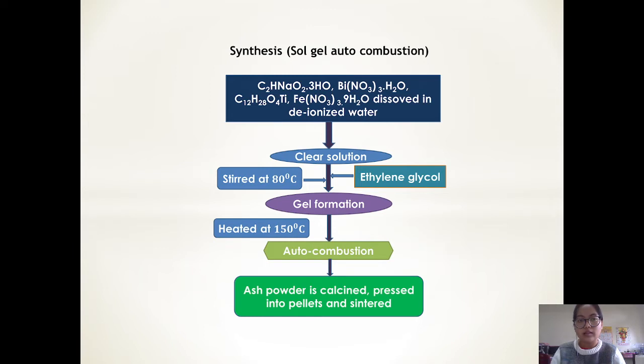This is the synthesis process, that is, the sol-gel autocombustion method. The precursors we used were sodium acetate, bismuth nitrate, titanium isopropoxide, and iron nitrate. These precursors were dissolved in deionized water and stirred continuously for 2 hours at 80 degrees Celsius to get a homogeneous solution. Ethylene glycol was then added in the required proportion and gel formation takes place.